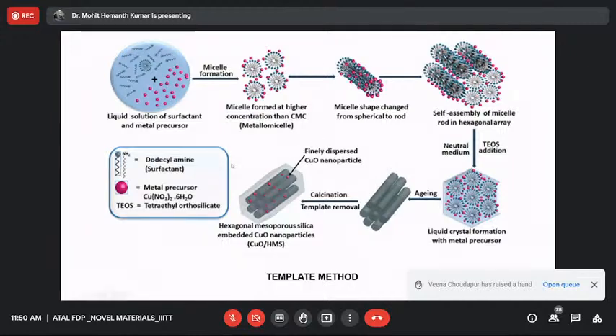We mix a liquid solution of surfactant and the metal precursors together to form micelles. A micelle is a different type of structure at a higher concentration. That means we are mixing a chemical liquid surfactant, in terms of atoms, and this has been shaped in the form of spherical rods. And now finally they have been converted into a liquid crystal formation with the metal precursor. Then aging occurs. Finally calcination occurs in order to obtain the copper oxide nanoparticles. So this is one type of method for producing a nanoparticle.